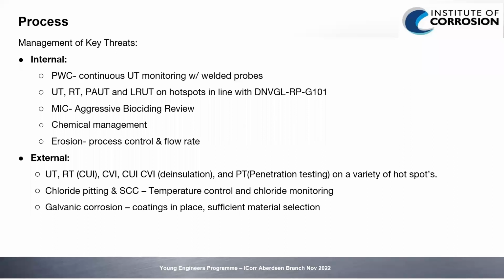So internally, in terms of preferential weld corrosion, we believe installation of continuous UT monitoring probes would help here. This, along with inspection activities on the hot spots such as UT, RT, phased array and long range UT. On the MIC threats, we believe a full chemical review is required to understand why the biociding is not acting as we'd like it to, whether we require some further chemical injection or what needs to change there. In terms of the erosion, we believe we need to have some conversations with process engineers to understand whether we can modify the flow rates in places to minimize that threat going forward.